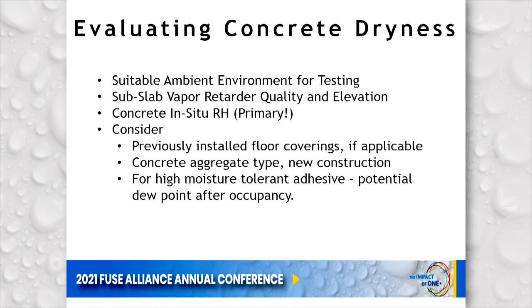So if we start talking about how we're going to evaluate concrete dryness and really evaluate it, we need to know and document suitable ambient environment for testing. We need to know that there's a subslab vapor retarder. We want to know its quality and its elevation. Is it directly under the concrete? We do want that in situ relative humidity information because that is primary. And then we need to consider previously installed floor coverings, if applicable. We need to know if it's new construct, what the concrete aggregate type is. Is that going to affect our test results? And for high moisture tolerant adhesives, we need to be worried about the potential of dew point after occupancy. And we're going to talk about that for just a minute as we follow up on these things.